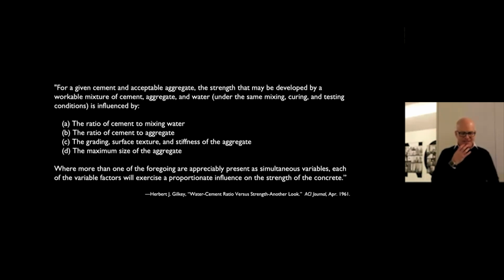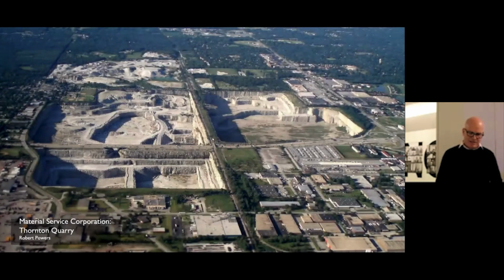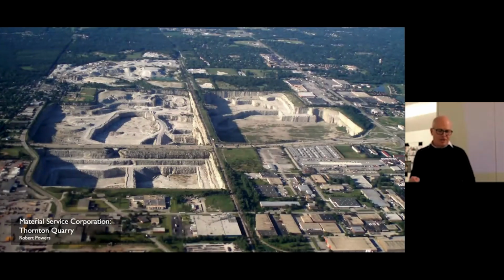What Gilkey argued was that yes, the ratio of water to cement is vital. Abrams was right about that. But he says that there's a lot of strength left to be had by looking at the proportion of cement to aggregate and by looking at the aggregate itself. So what is the strength of the aggregate? What's the size? What's the texture or roughness of the aggregate? And how big can you get it? And this turns out to be key to the huge jumps in strength that we see in the 1960s and 70s. Some of that is geologic.